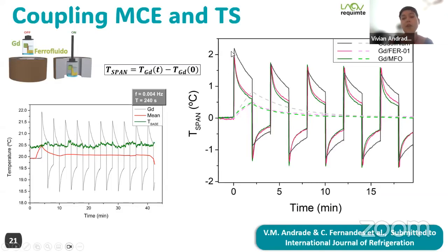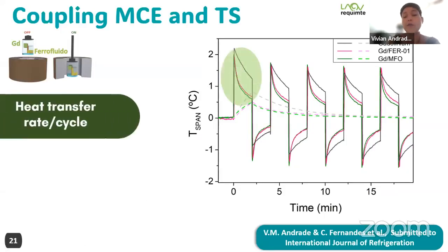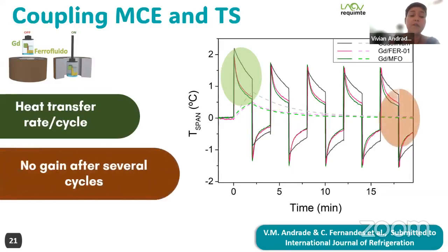And we have here 3 measurements: the gadolinium alone, and the gadolinium in contact with the ferrofluids, as you can see, and the dots are from the movable mean temperatures. So the first thing we note is the heat transfer rate per cycle is larger for the system coupled with the ferrofluid. However, after several cycles, there's no gain in the temperature span.